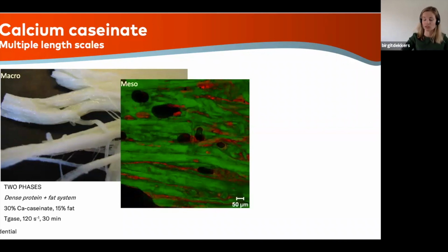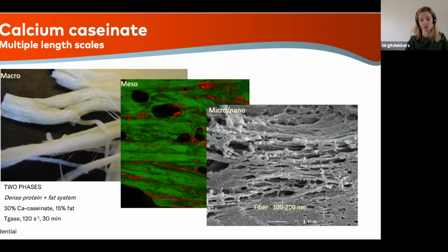So on a macroscopic scale, you could of course see these nice fibers, but also if you start looking with, for example, confocal scanning laser microscopy, you could see this nice anisotropy and these fibrous strands. Here you see in green the protein phase and in red the fat phase. And how you could structure basically with a shear cell these types of materials. If you zoom in even further, with a different microscope, in this case scanning electron microscopy, you could see that you have structure formation down to a very small length scale, 100 to 200 nanometers. You see anisotropy of the proteins.